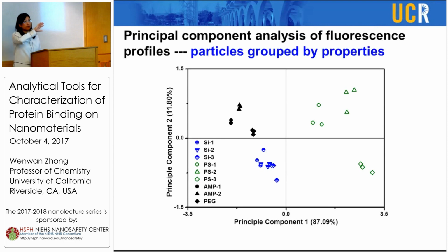And if we use the fluorescence profiles for all particles, and here we have a total of 9 types of particles, we see the fluorescence profile can group the particles very nicely by their core materials and also by their sizes. So if you look at the green signs, those are the polystyrene particles.